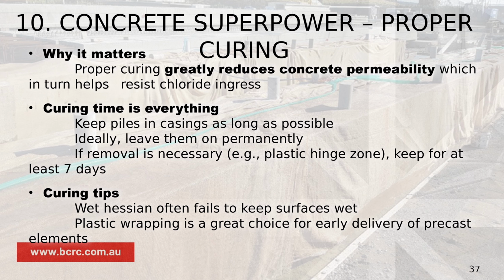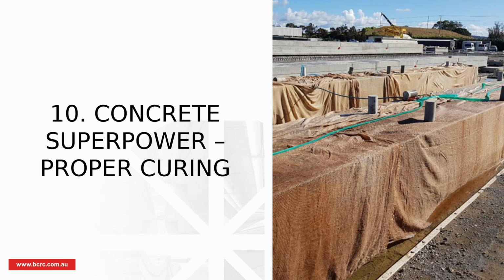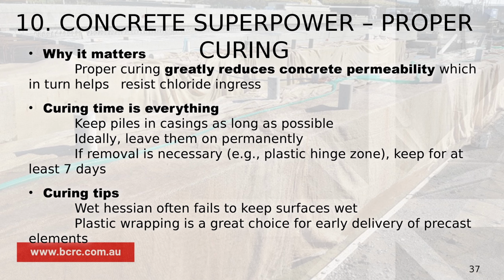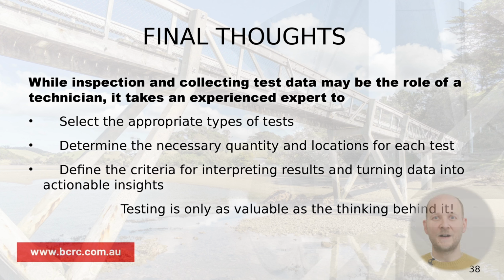A couple of tips here, and I would like to get a picture I already showed you, which illustrates an element with a Hessian cloth on it. I would recommend to inspect those elements very well. What I did find in this particular case was that about 50% of the area of this element was dry, with the entire underside not being wet cured. Also, if you're dealing with precast elements which have to be delivered green on site, consider plastic wrapping. Plastic keeps moisture in and allows your element to cure very well. And to illustrate this point, you could wrap in plastic almost everything, as you can see here an example of a few boards.